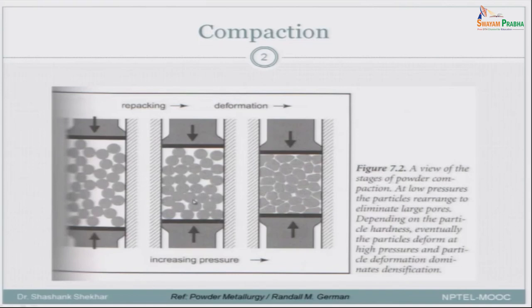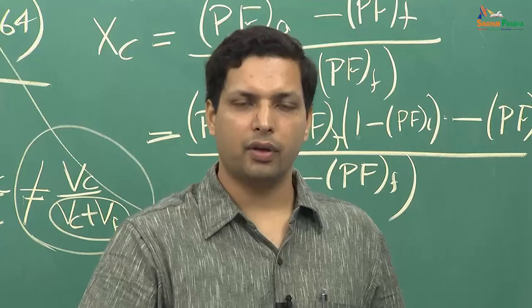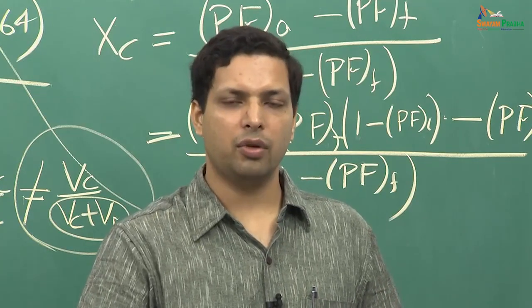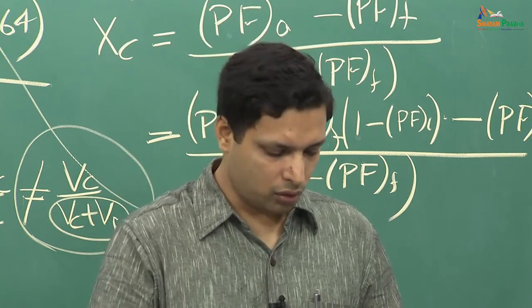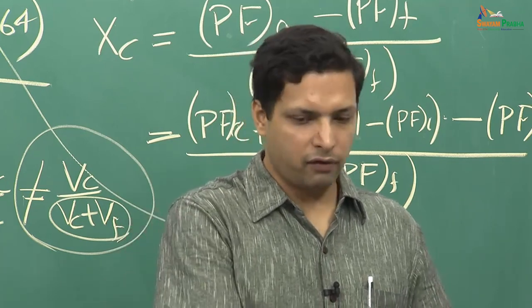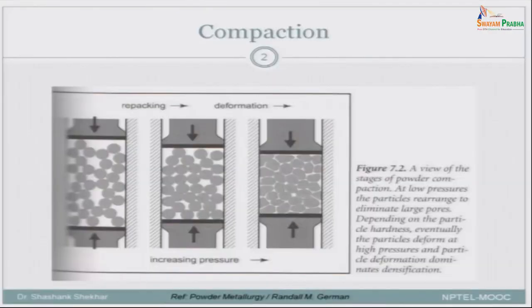This rearrangement gives a much larger improved packing fraction, so initially there will be a large increase in relative density. If you keep on applying pressure, deformation starts to increase. When material deforms, it becomes strain hardened and will have a higher flow stress, so higher and higher pressure is required to deform it further. So there are at least two steps: one of repacking and another of deformation.